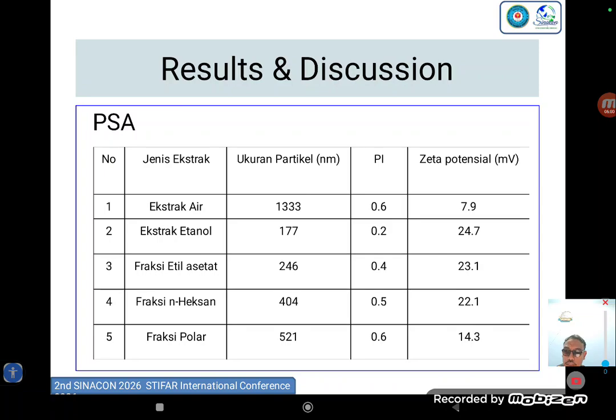Next, we evaluate the physical characteristics of the synthesized nanoparticles using a particle size analyzer, or PSA. Interestingly, both the ethanol extract and other organic fractions produce well-sized nanoparticles along with a relatively high zeta potential value, which indicates excellent colloidal stability. In contrast, the water extract yields very large particles and a low zeta potential. This strongly confirms that organic components in ethanolic extract act as a much more effective capping agent.